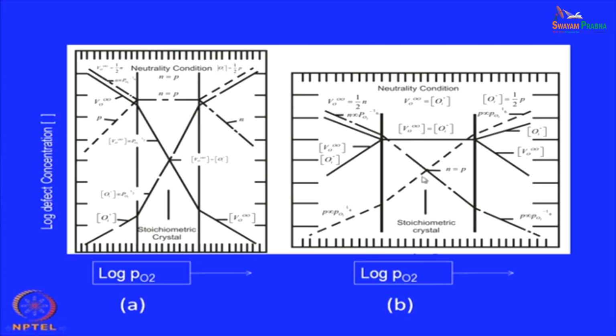This is Kf and this is Ke. So, here Ke is much smaller than Kf, whereas here Kf is smaller than Ke. So, this corresponds to Ke, the electronic compensation, and this is the ionic compensation. So, the ionic compensation is less important here, electronic is important here, electronic is less important there, ionic is important.